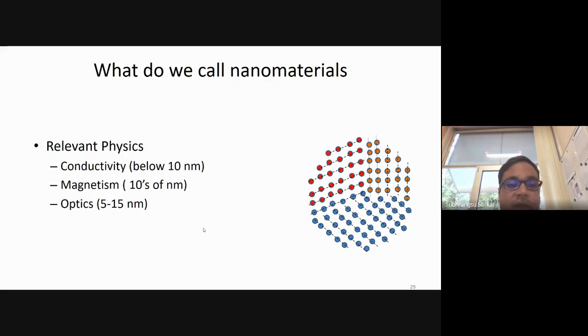For example, if we are talking about electrical properties of metal nanoclusters, typically the range of interest would be below 10 nanometers of particle size. Ferromagnetic materials like iron or stuff like that become superparamagnetic when we reduce their particle size below tens of nanometers, let's ballpark 30 to 40 nanometers. On the other hand, if someone is interested in looking at quantum confinement in optic systems, like quantum dots and stuff, then the relevant particle size limit would be 5 to 15 nanometers. So there is no direct size limit below which we'll say, yes, this is obviously nanocrystalline, or it's a nanomaterial. No.